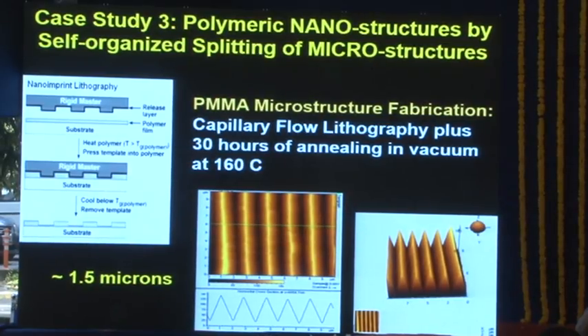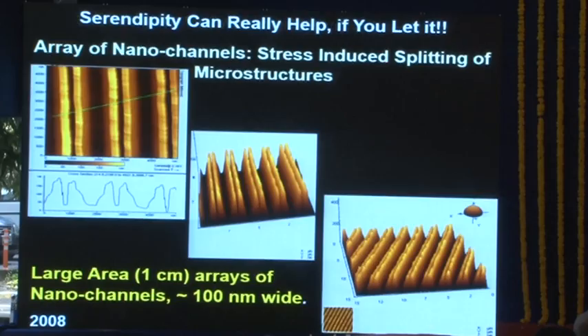You see that triangular microstructure there, which is well and good, except that after some time, this structure breaks. Starting from the top, the pyramid splits into two parts. So this is what was happening in the experiments, and this made the student very desperate, very depressed for many months. But he would not come back and tell me, he would just keep telling me that the experiment doesn't work. I throw away all these samples. So this is what was happening.